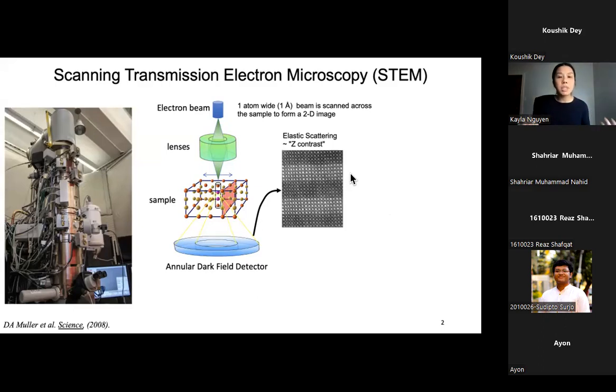If you look at these images here, what you see are really dark atoms and really bright atoms. Materials that have a bigger Z element, something heavier like lead or bismuth, will show up brighter because they scatter more at higher angles. Whereas lighter materials, in this case maybe strontium or titanium, show up darker because they don't scatter to as high of angles on an annular dark field detector, as the heavier Z elements do. And that's really cool because we can image atoms.